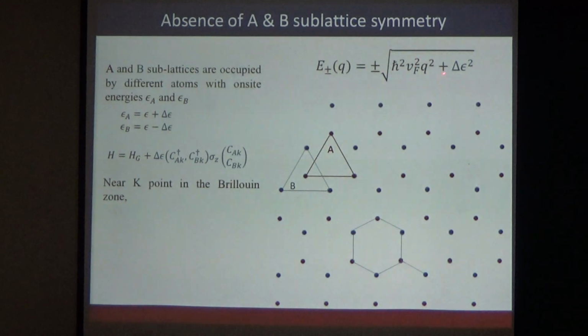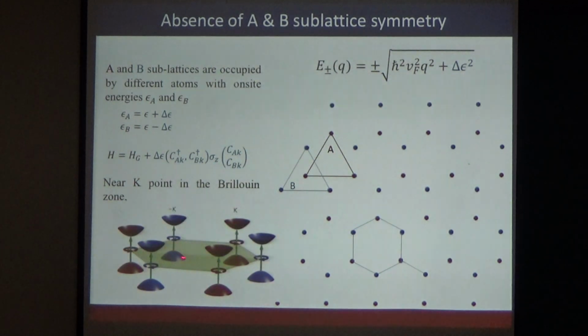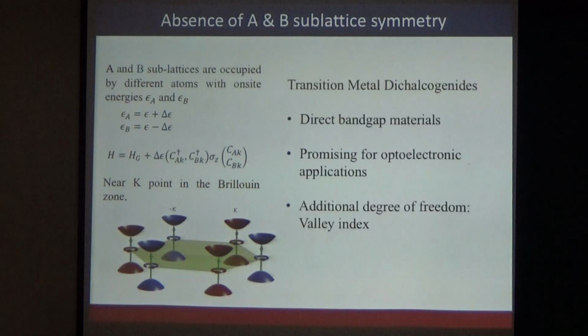So now you'll see that there is no point in the Brillouin zone where the band gap vanishes, right? So this is what will happen at those k and k prime points. We'll open up a band gap just because the sublattice symmetry is broken. And this will also give rise to an interesting effect, because at these particular points they have non-trivial pseudo-spin, non-trivial pseudo magnetic moment associated with the regions very close to the k and k prime points, which was 0 in the case of graphene because of the sublattice symmetry. And now this material becomes very interesting because this is a direct band gap material.